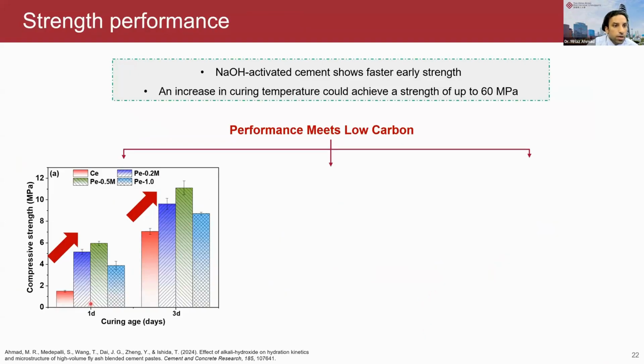You can see here, the results are quite promising according to our testing. The NaOH, the sodium hydroxide, technique significantly increased the early strength from 1.7 megapascal to around 6 megapascal at 1 day, which is more than 3 times. So it's a significant improvement in compressive strength, and by 3 days, it can reach around 11 megapascal.